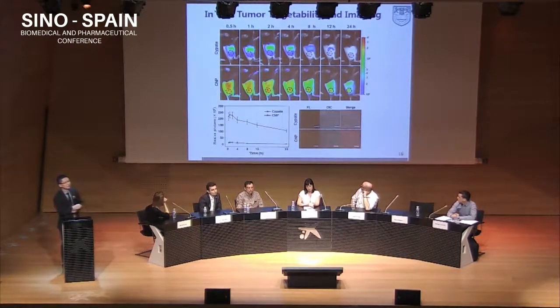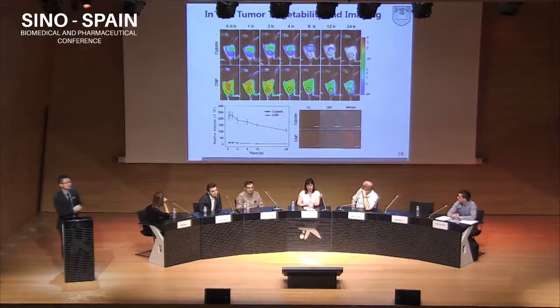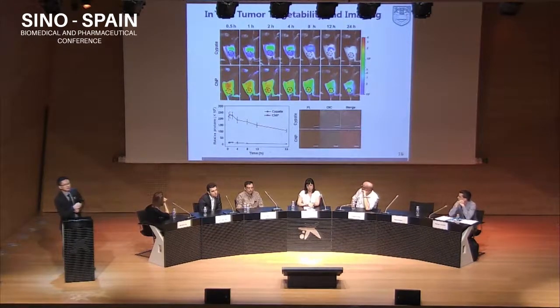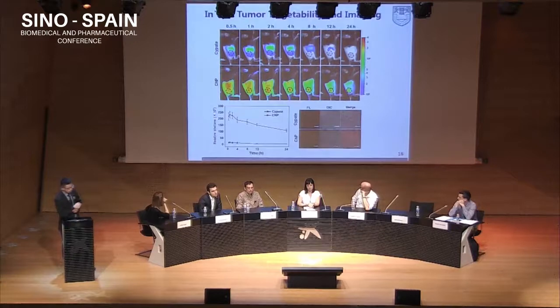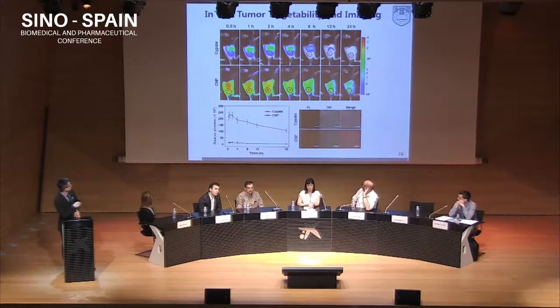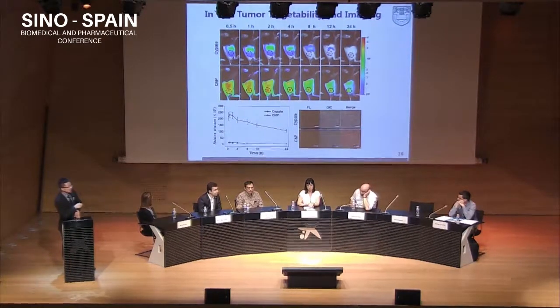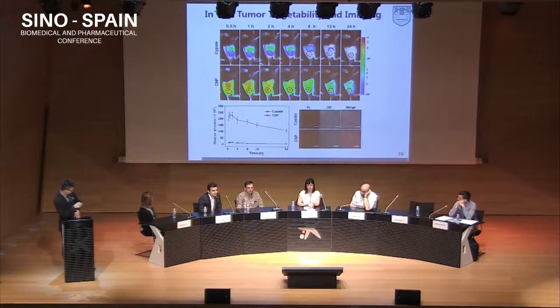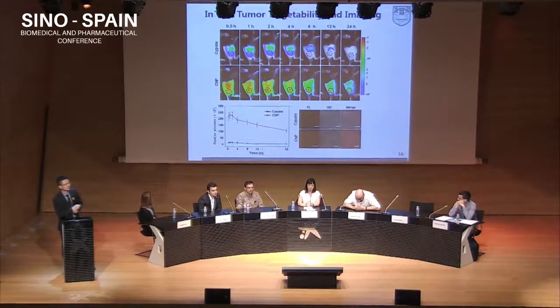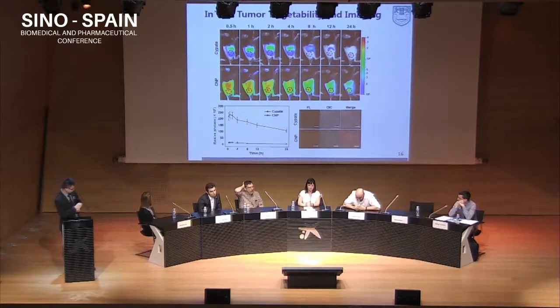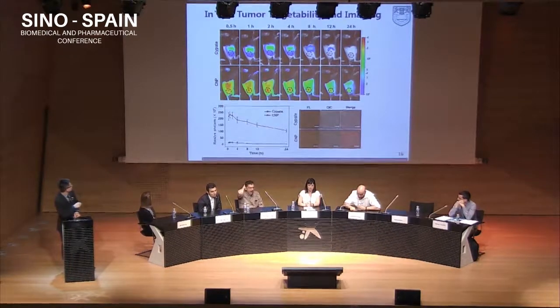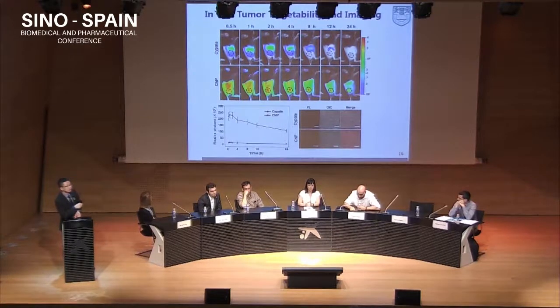And for the in vivo imaging system, we injected the free dye and our nanoparticle into tumor-bearing mice, and we found that in the case of free dye, we cannot easily detect the tumor, probably due to the long circulation time and the poor tumor targetability. However, in the case of our nanoparticle, from 2 hours to 24 hours, we can easily detect the tumor by fluorescence imaging system.